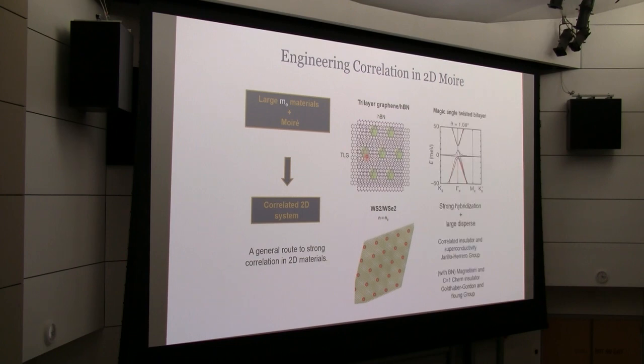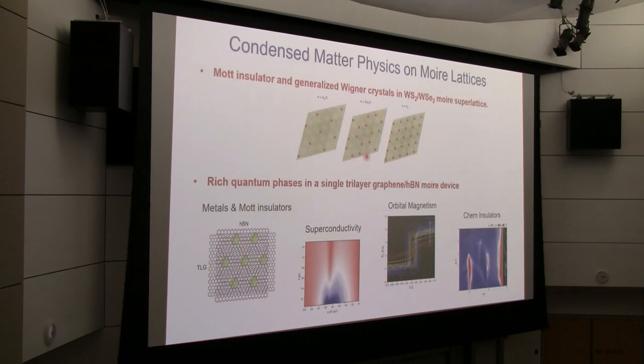This, to some extent, contrasts to magic angle twisted bilayer graphene, which requires a pretty subtle effect. You need a specific magic angle. By using large Moire superlattice, there is really no magic. You can use it in almost any material. In the case of transition metal dichalcogenide, we can make Mott insulator and generalized Wigner crystal. And for trilayer graphene, it has tremendous tunability. You can realize Mott insulator, superconductor, magnetism, and Chern insulator all in the same device by applying electric field. So this will be a really nice model system to study how the different phases get stabilized, how they compete with each other, and how the phase transition happens between different states.